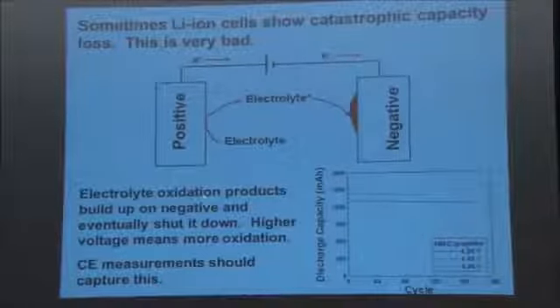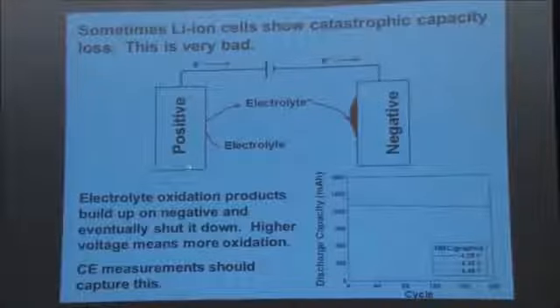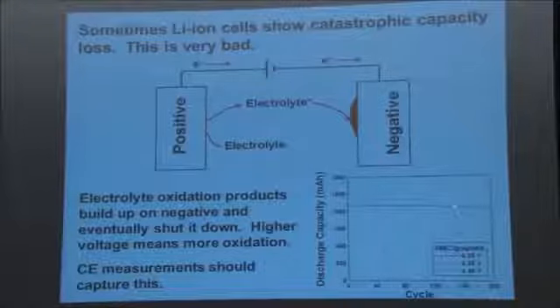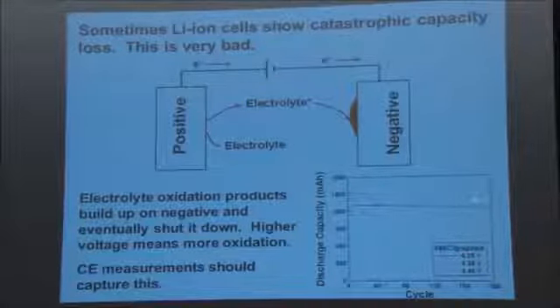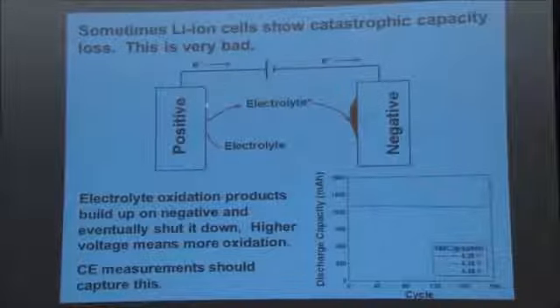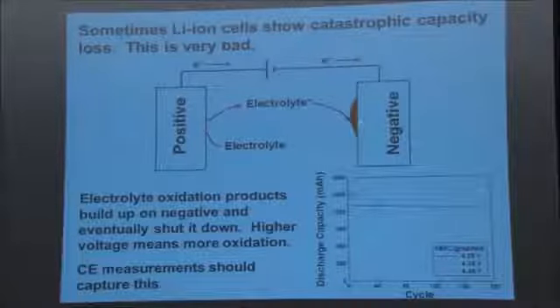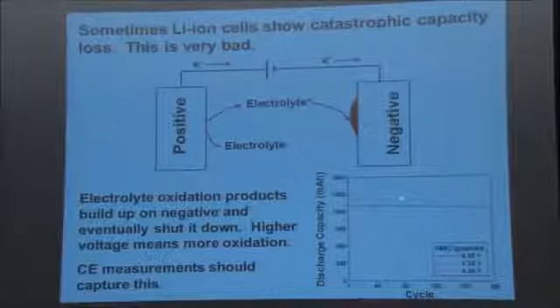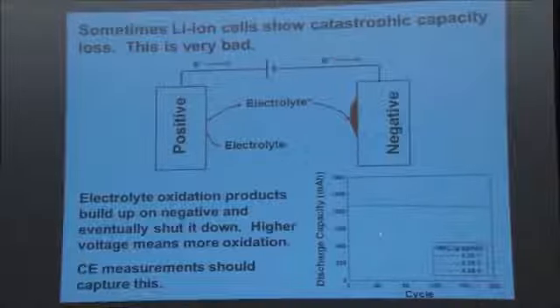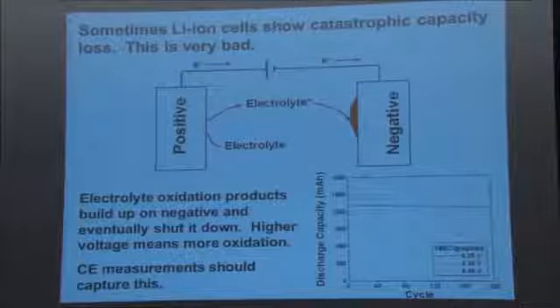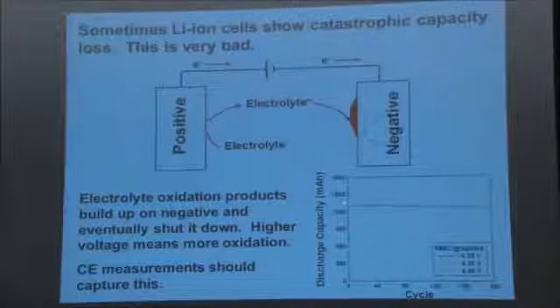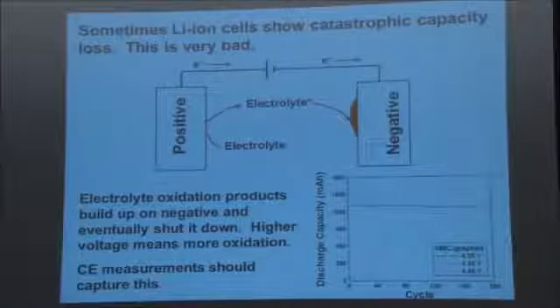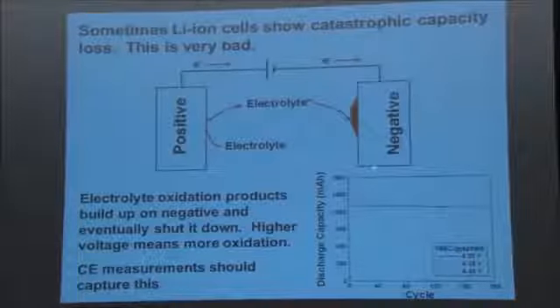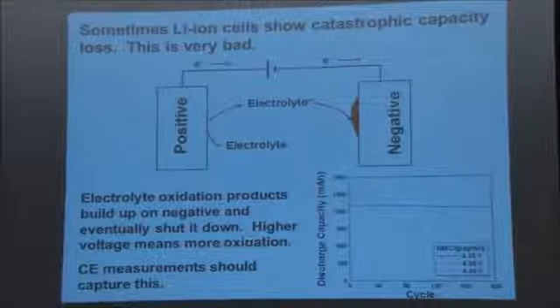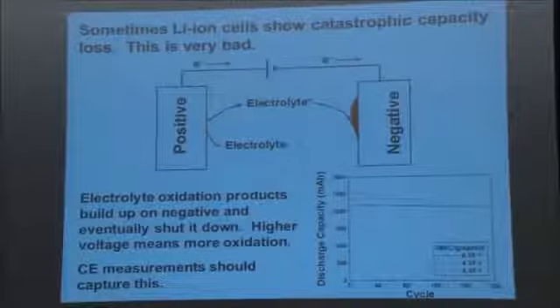We believe that this rollover or catastrophic failure comes about because of electrolyte oxidation at the positive side. There's no significant capacity fade here at all, so lithium's not getting consumed in the SEI at the negative. By contrast, the electrolyte's getting oxidized, oxidation products move to the negative, and they coat across the surface of the negative, and eventually they shut the cell down. Now, if you charge to higher and higher voltage, you accelerate electrolyte oxidation, and this catastrophic failure moves to lower and lower cycle numbers, as you can see. So the point of this is a great test bed for our methods. Coulombic efficiency measurements should capture this and should be able to predict the onset of catastrophic failure.